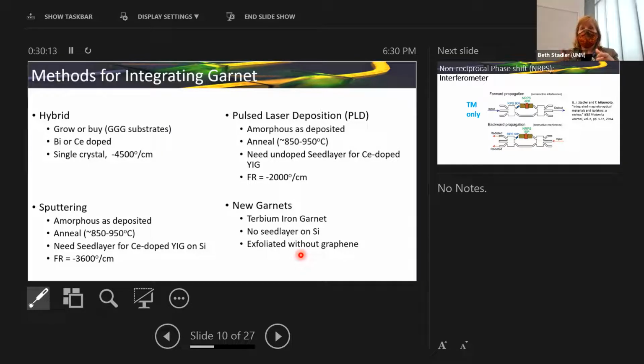Get a single crystal substrate, put a sheet of graphene. A film can grow on top of that epitaxially, basically, and be peeled off, but then you've got the graphene there. So we were kind of thinking, well, this is really neat. We can exfoliate without that graphene. So if you want to look that up, they're calling it remote epitaxy.